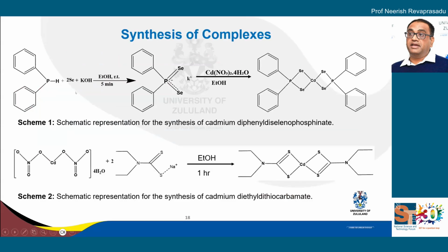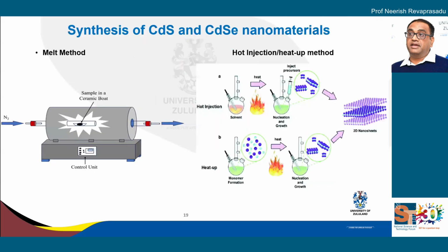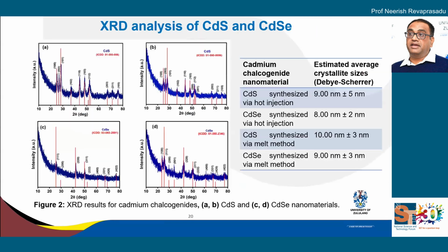Firstly, to make the quantum dots, we again use the single source precursor method. We use different complexes, and these are the examples. These are for more chemists. And how do we make them? The hot injection route is the most popular route to make high quality quantum dots, where you dissolve your precursor in a solvent and have a nucleation and growth process, and then you collect your material through flocculation and final dissolution in a suitable solvent. So we have them in solution form, where we can then study them further.